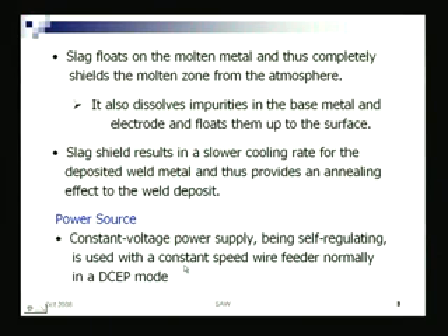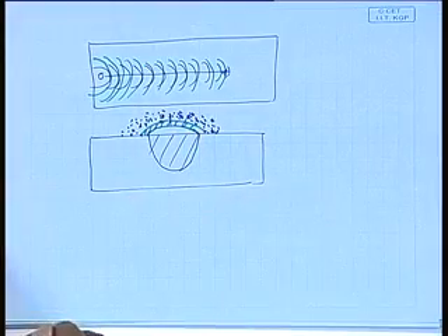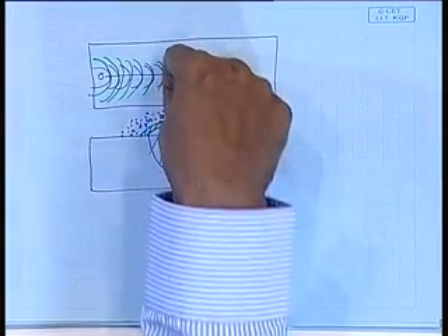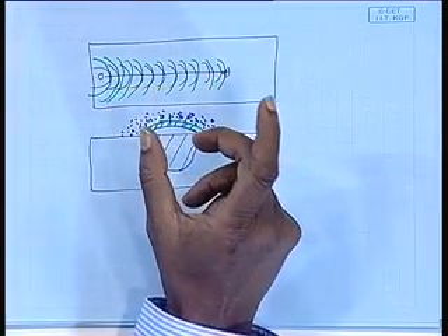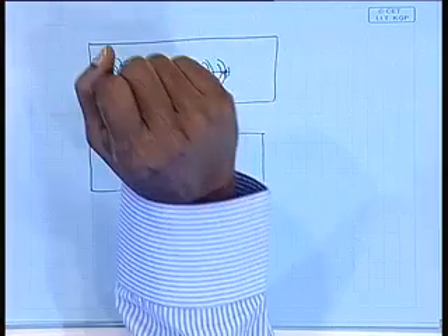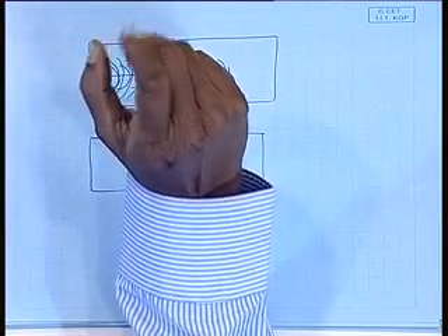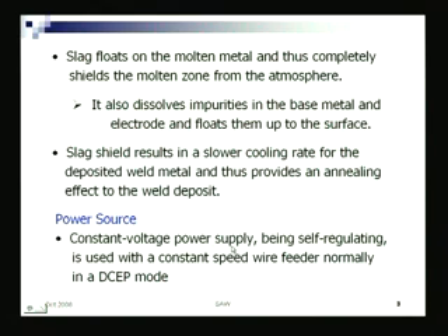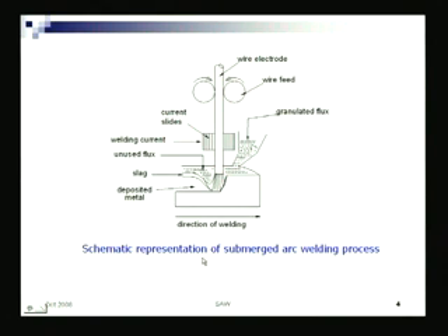Why? I want to deposit more metal. By increasing penetration with DCEN, I can increase penetration, but I do that by increasing current, and keeping the electrode positive, I melt more electrode, thereby increasing the deposition rate, because I have to increase deposition rate and welding speed for increasing productivity. So it operates at CV, or constant voltage power supply, with DCEP mode.